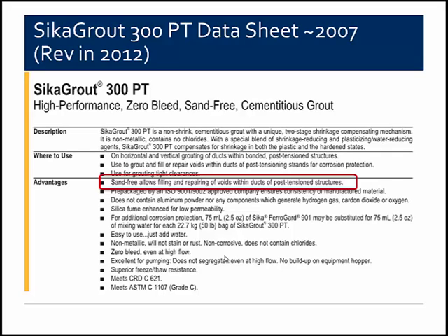This is a copy of a data sheet from the SikaGrout 300PT from about 2007. They revised it in 2012, and I've highlighted on here this bullet where they say it's sand-free. The reason I highlighted that was that it was a significant difference between the first generation and the second generation grout. The original first generation grout had a microfine silica sand in there as a filler, and I believe reports were coming back to the manufacturers at the time that sand was causing damage or wear to the pumps and the mixers used to mix this grout. And so the second generation grouts produced by most of the manufacturers generally took out that microsilica sand.